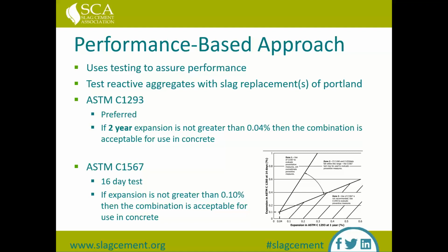One caveat with the C1567 test - you can see in the lower right there's a chart, and that chart's comparing the C1293 result with the C1260 result. And if these 2 results line up in that zone 3 with the diagonal markings, then it's not recommended to use the 1567 test. All right, next slide please.